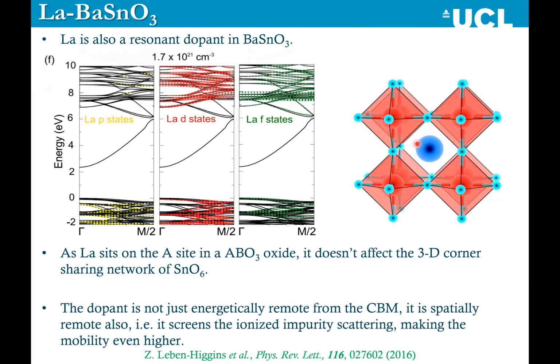And this explains why barium stannate has the highest mobility of all TCOs at 320. It's simply the same doping mechanism that we only discovered last year and the year before, but can actually be used to explain the high performance of lanthanum doped barium stannate.